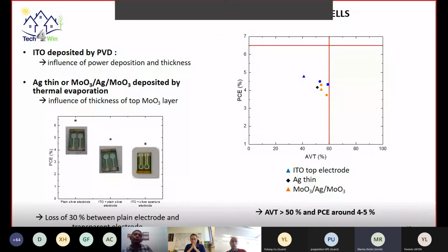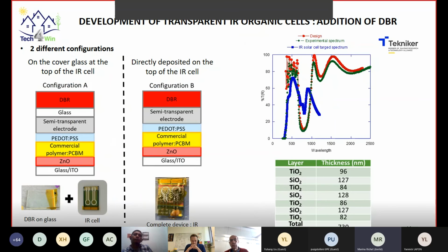And we can see also that the molybdenum oxide allows us to increase a little the performance and a little the transparency. So except for one ITO top electrode, the transparency is always superior to 50%, and the PCE is around 4 to 5%. So in the project, in order to increase the performances, we decided to add a distributed Bragg reflector. This DBR is designed by Tekniker, and as we can see, it is adapted to the infrared solar cells developed in Tech4Win.